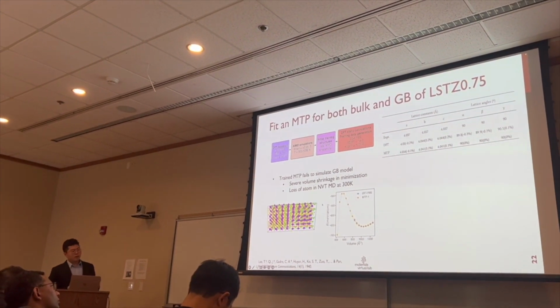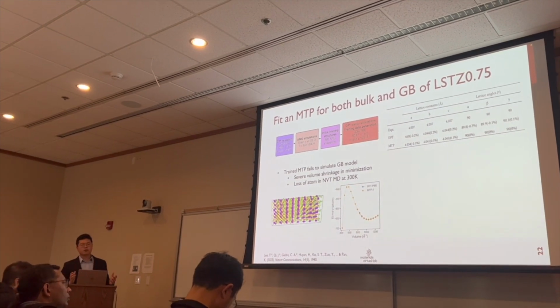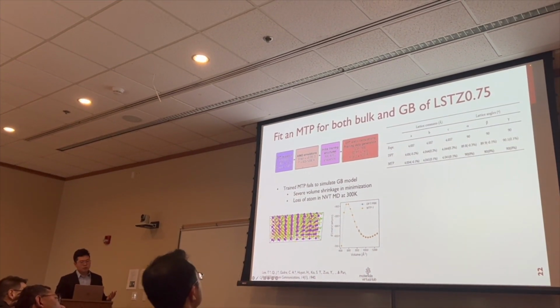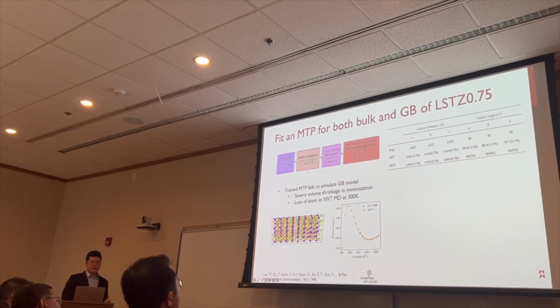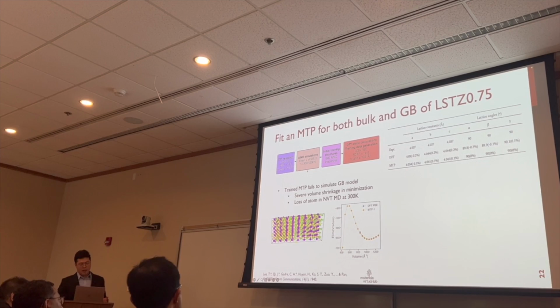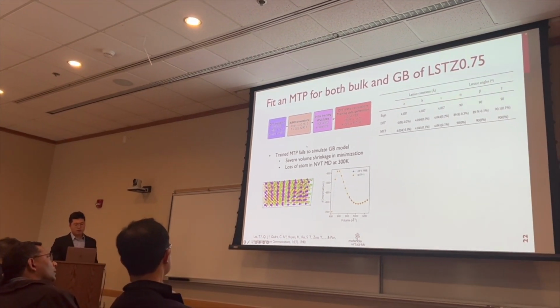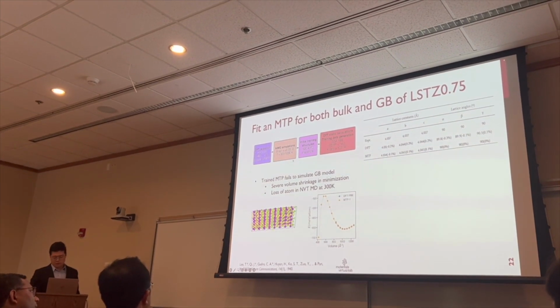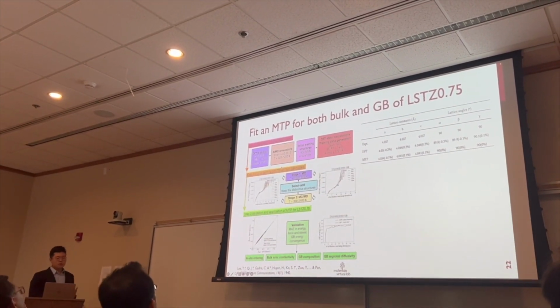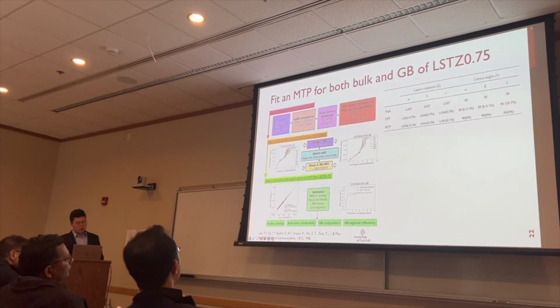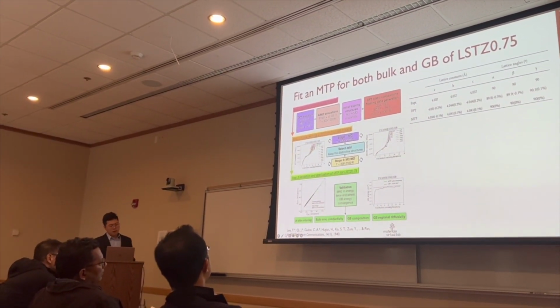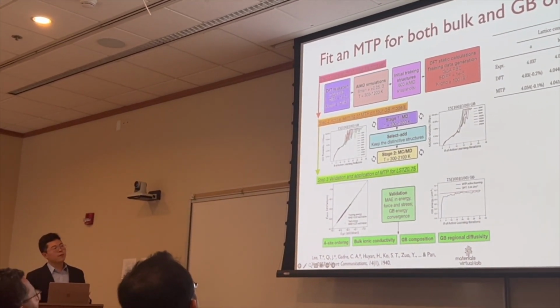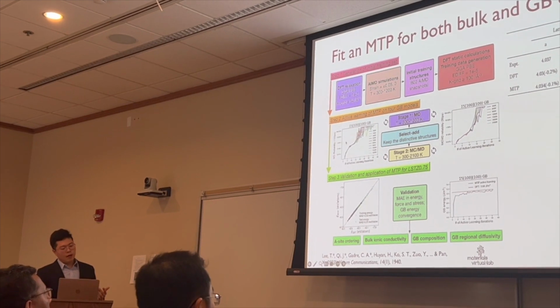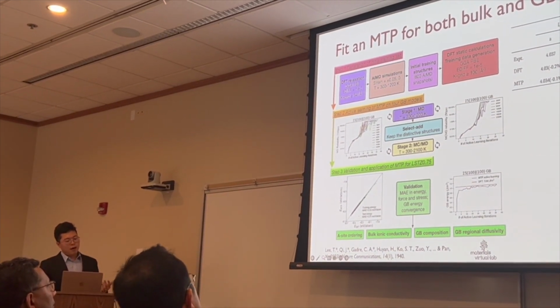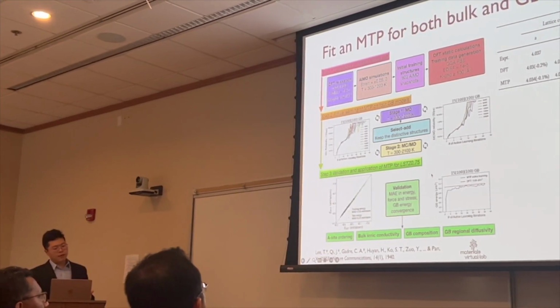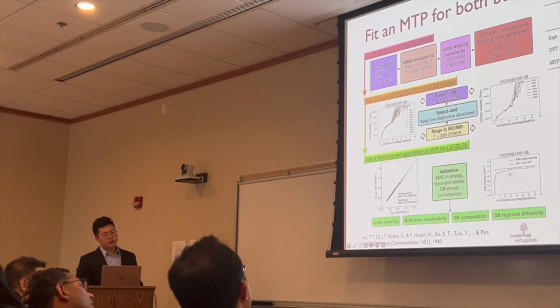So it tells us that we need to augment the training set to have broader coverage. So how do we do this? It's definitely very expensive and more or less unaffordable to do AIMD again for these large grain boundary structures that usually have over hundreds of atoms. So this time we use the active learning workflow that we discussed in the introduction to sample diverse structures. And you can see that with iterations of active learning, we get improved simulation reliability. And also our prediction for grain boundary energy converged to the DFT result after the active learning iterations.